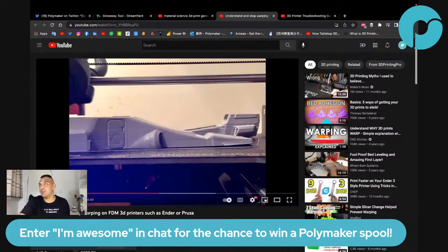If you print a large flat plate in ABS and hit one side with a heat gun, it will warp. But if you don't get it above the Tg, it will cool flat again. Okay, so you can take a video. You print an ABS part, like a cube, and put it on a 90 degree bed. If you print on a 60 degree or 70 degree bed, usually ABS will still warp, right? So what if you print the cube and you put it there? It's not a great experiment, actually, because it skips a lot of steps. So just forget about this.